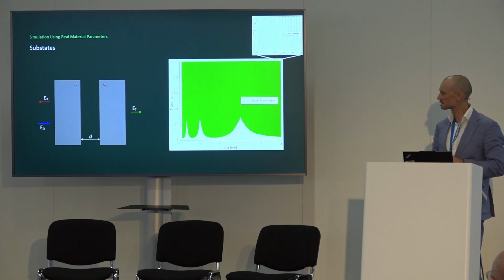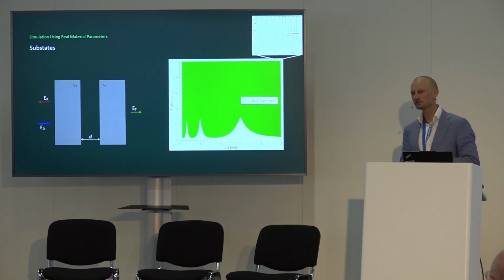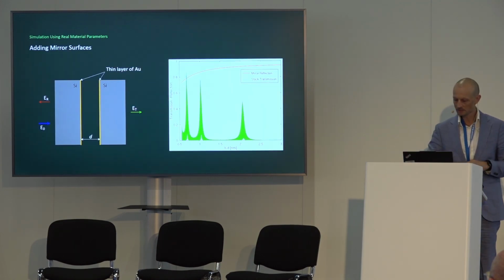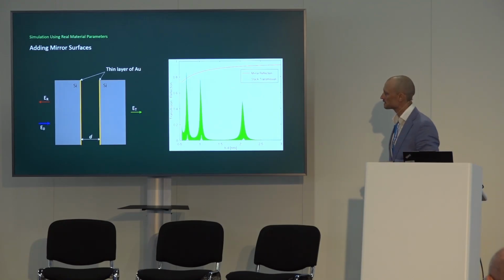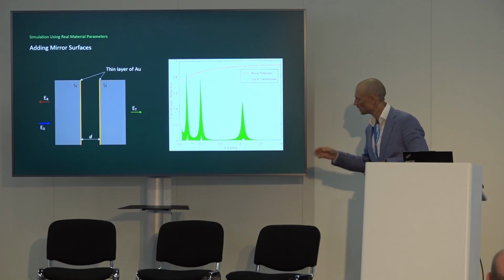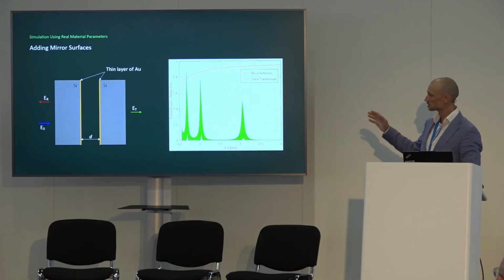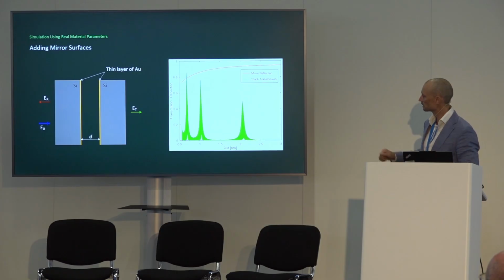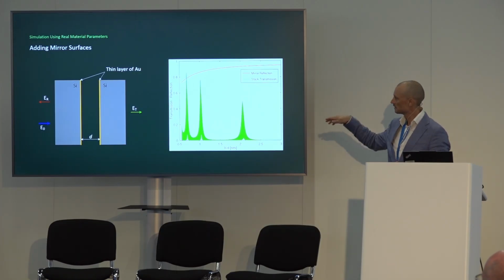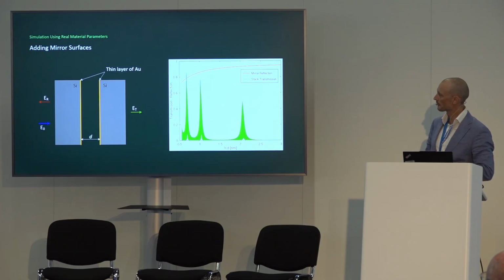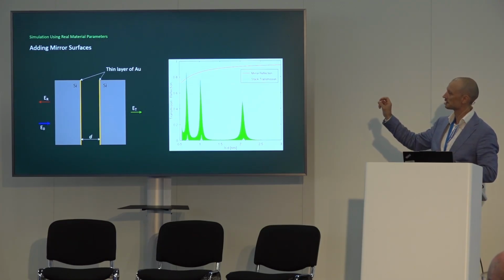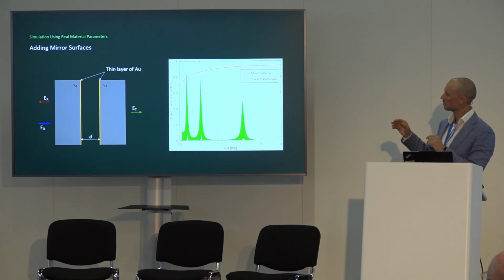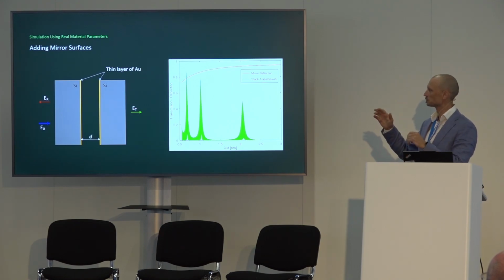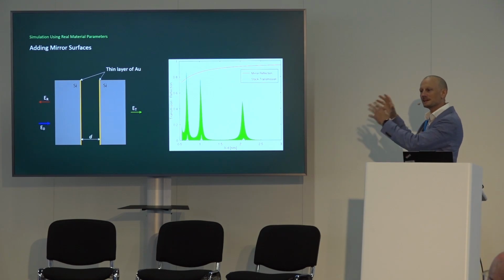So two silicon wafers, starting with that, sending the light in from the left, obviously does not give you the theoretical transmission, right? It looks very different. So we'll start by adding some high reflective surfaces on the inner sides of these silicon slabs. And at that point, you can start to see some features that are kind of similar to what we saw in theory. But you still have this high frequency component on top of these slower resonance peaks. And that's because of the parasitic resonances that remain in the silicon slabs themselves. So to solve that, we have to introduce some anti-reflective surfaces in order to only have the gold surfaces remaining in our optical system.